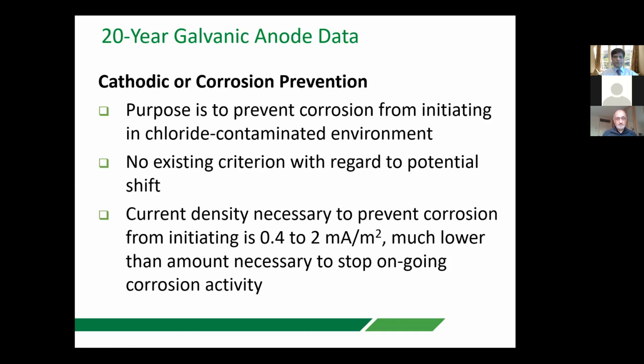The only thing that is mentioned in the standard is that the current density necessary to prevent corrosion from initiating is between 0.4 and 2 milliamps per meter squared. And that is much lower than the level required to stop ongoing corrosion activity. And that's more like 2 to 20 milliamps per meter squared. So it's an order of magnitude lower current requirement.